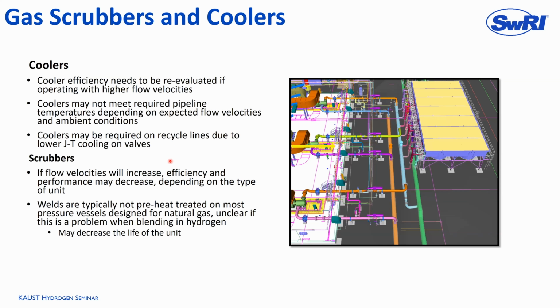A couple of the last things on gas compression systems. There are a lot of coolers, scrubbers, vessels, valves, etc. We expect that there will be other changes needed to a pipeline compressor station to accommodate hydrogen blending. If you're increasing volumetric flows, then coolers will become less effective because they have less time to affect their heat transfer. Coolers are also sized, assuming in some cases that there's a temperature drop across valves through Joule-Thomson cooling. As you blend hydrogen in, the Joule-Thomson coefficient decreases in amplitude, so you get less cooling.